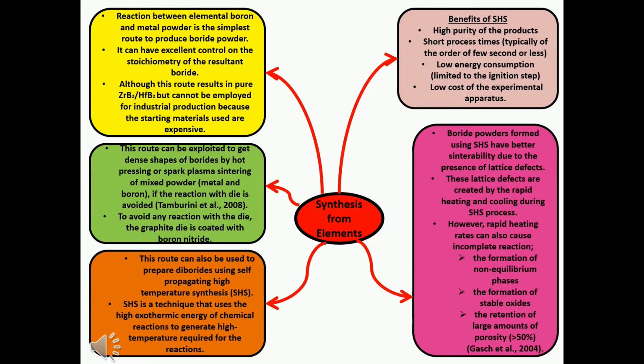SHS is a technique that uses the high exothermic energy of chemical reactions to generate the high temperature required for the reactions. Benefits of SHS: high purity of the products, short process times, typically of the order of a few seconds or less, low energy consumption, limited to the ignition step, low cost of the experimental apparatus. Boride powders formed using SHS have better sinterability due to the presence of lattice defects. These lattice defects are created by the rapid heating and cooling during the SHS process. However, rapid heating rates can also cause incomplete reaction.